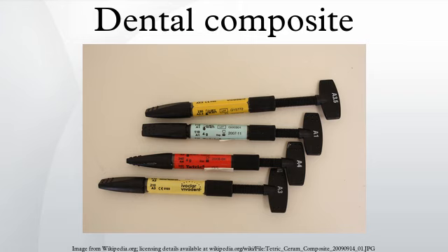The dentist should place composite in a deep filling in numerous increments, curing each 2–3 mm section fully before adding the next. In addition, the clinician must be careful to adjust the bite of the composite filling, which can be tricky to do. If the filling is too high, even by a subtle amount, that could lead to chewing sensitivity on a tooth. A properly placed composite is comfortable, aesthetically pleasing, strong and durable, and could last 10 years or more.